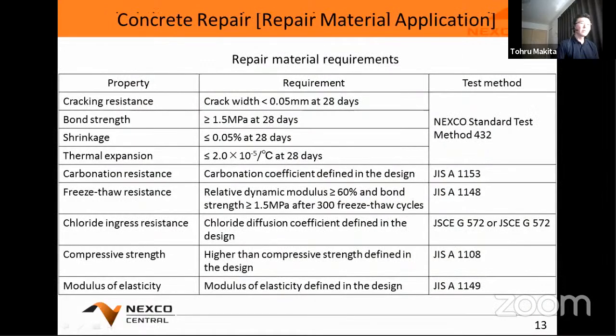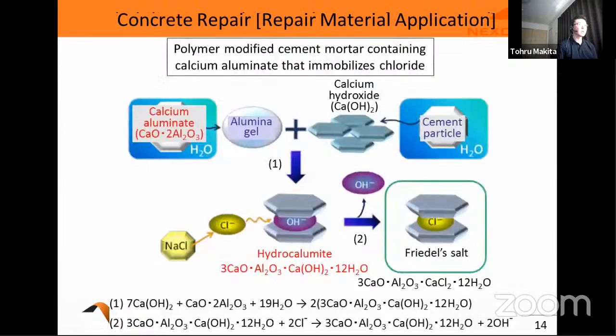So after removing deteriorated concrete, repair materials are applied. These are the requirements for repair materials prescribed in the NEXCO Central Construction Management Manual, which I previously mentioned. Usually polymer modified cement mortar is used as repair material. But nowadays, higher chloride ingress resistance is often required for repair materials to minimize life cycle cost of concrete structures.